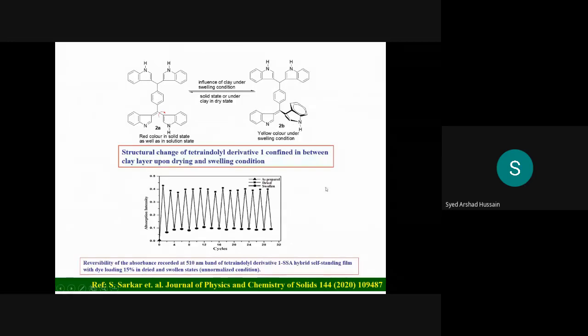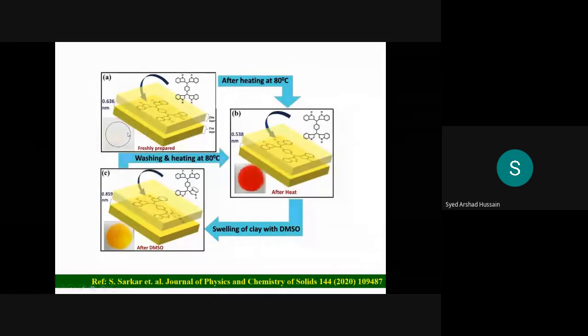So we confirm it by spectroscopy as well as measuring XRD and some morphological study also. Schematically here shown, this is in normal freshly prepared films. You see that the gap is of the order of 0.636 nanometer. Then in dried condition it's lower, 0.538 nanometer, so maximum flat. Again in swelling with DMSO you can see 0.459 nanometer, the gap increases, so some molecular twisting occurs, and accordingly color change occurs. So this is very good for optical memory applications.